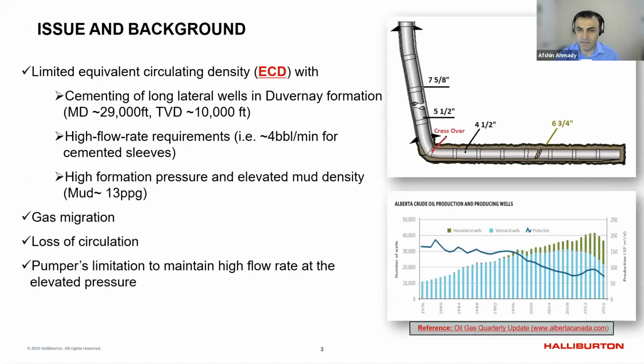Here is just the design for this well, intermediate and production, all the way down to around 29,000 feet. TVD was around 10,000. As you see, around 19,000 feet of lateral section, and 4.5 in 6 3/4 open hole. That was the big challenge, to keep the pumping rate as high as possible. For this specific design, they had cemented sleeves, and the pumping rate couldn't be less than 4 barrels a minute. That was dictated by the cemented sleeves company. They wanted to have momentum to keep the dart running through that restricted area.